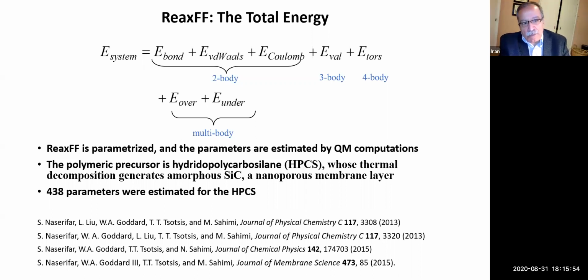So you parameterize all these expressions, and this force field had 438 parameters that we needed to determine based on quantum mechanical data that we calculated. So we did that, and in fact, we identified the optimal thickness so that when we actually did the experiment, indeed, that was the optimal thickness.